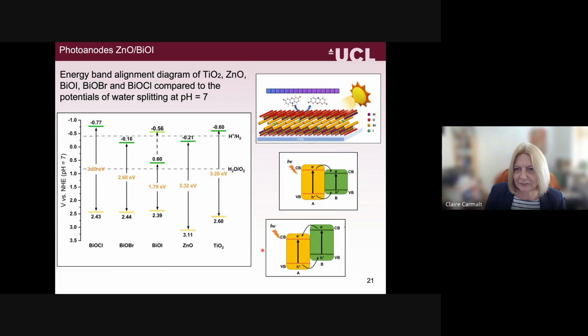We also were interested in heterojunctions, as I've mentioned previously, about trying to get the best heterojunction that you can form. So here's the bismuth oxybromide that I mentioned before. We looked at the band gaps of different materials, so the zinc oxide and the TiO2. We decided the zinc oxide had a good alignment, and heterojunctions can be good because when you irradiate with UV or visible light, and you get the electrons promoted from the valence band to the conduction band, rather than recombining, they can then transition to the other semiconductor in the heterojunction.